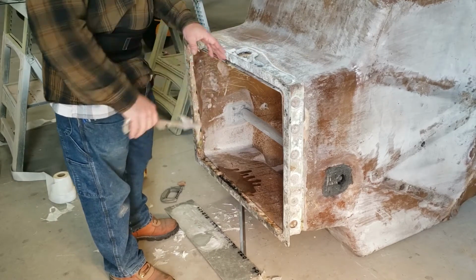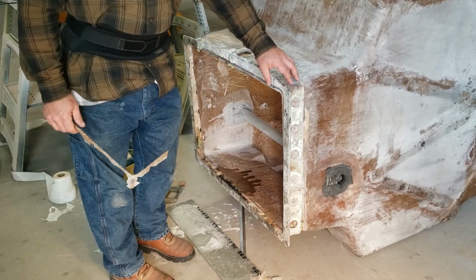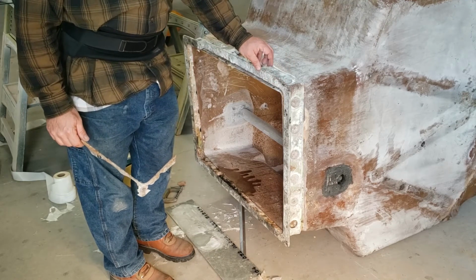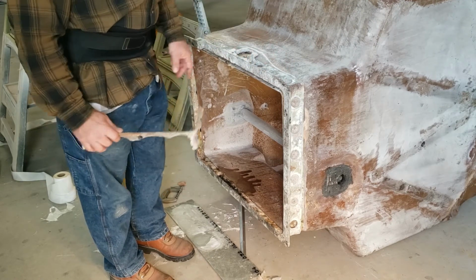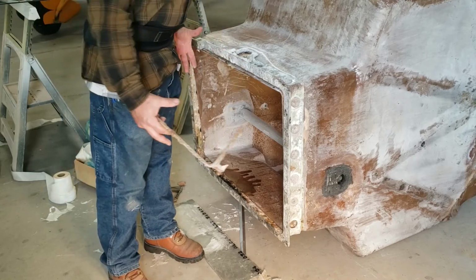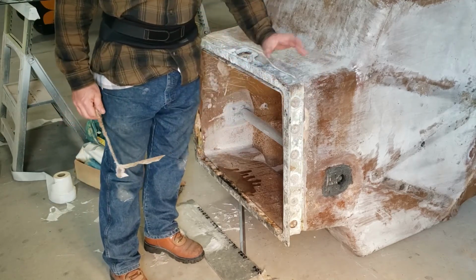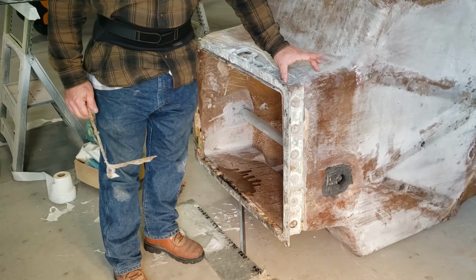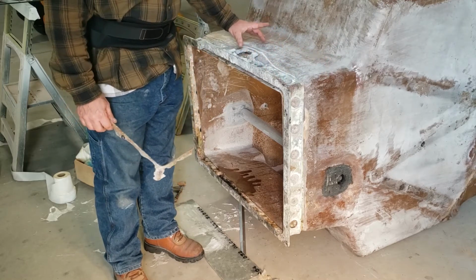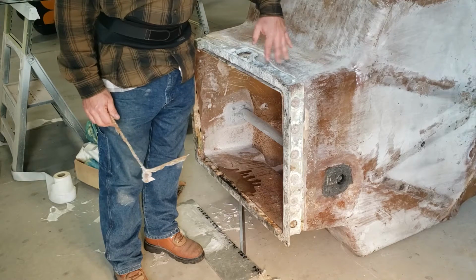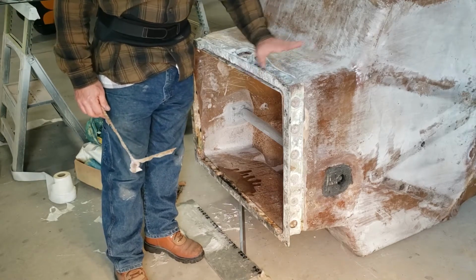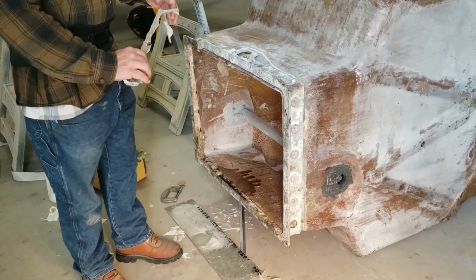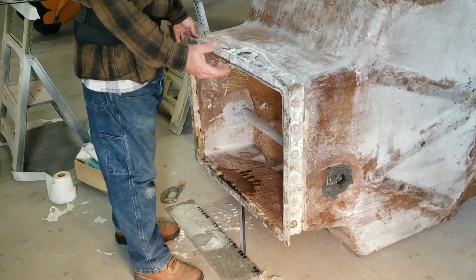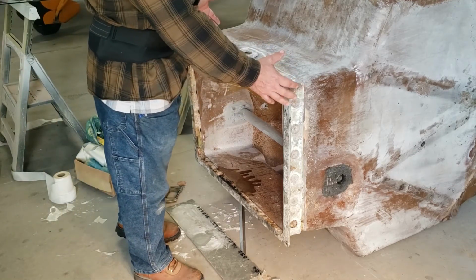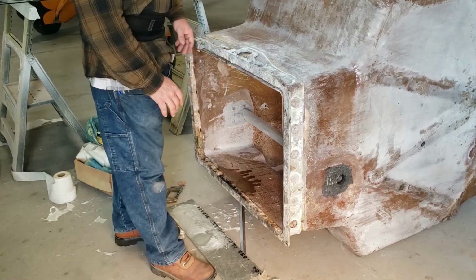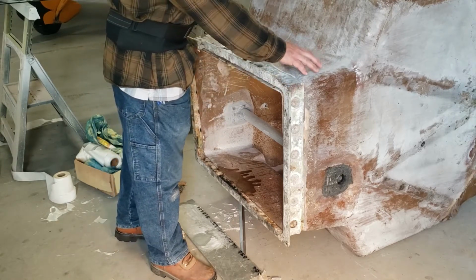Secondly, this aluminum flange was primed with a zinc-based primer. They primed it, they slid it up onto the hopper just like this, and then somebody used actually fiberglass matting and a polyester resin to wet out this and just attach this flange to the tank. Nice thing is it made it very easy to cut the flange off and remove it. The bad thing is this flange was never bonded to the tank.